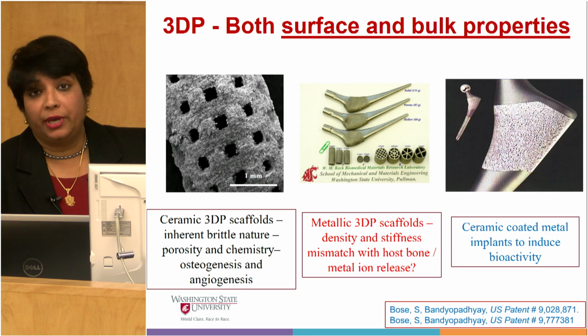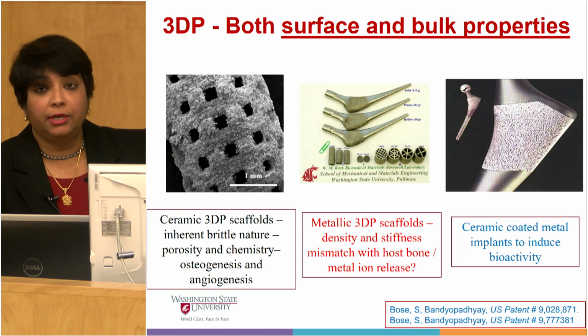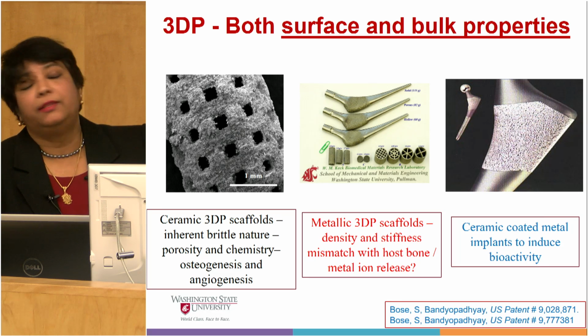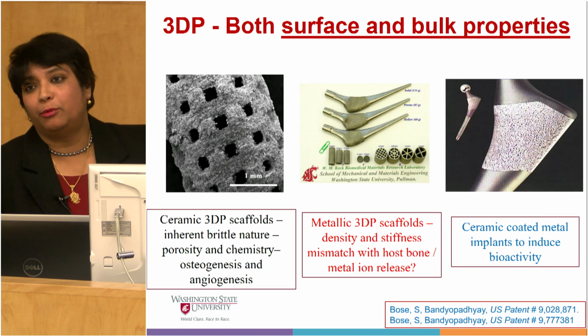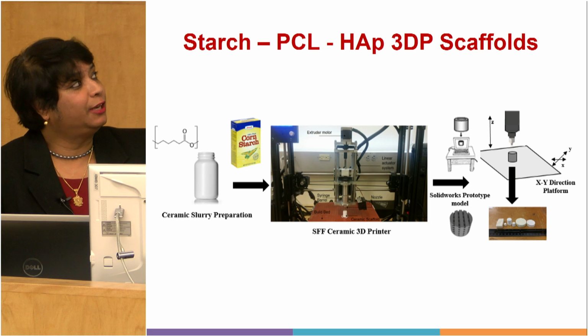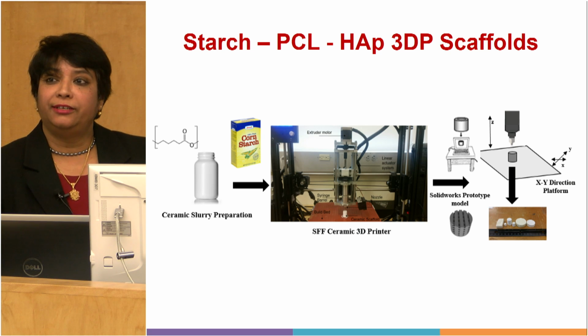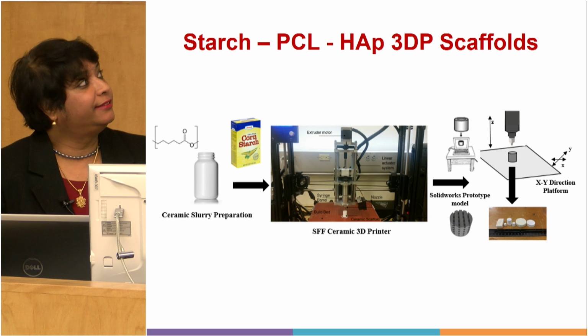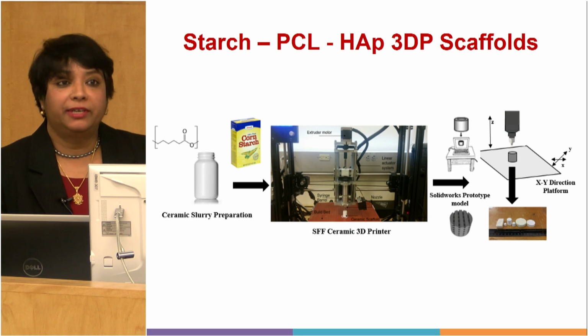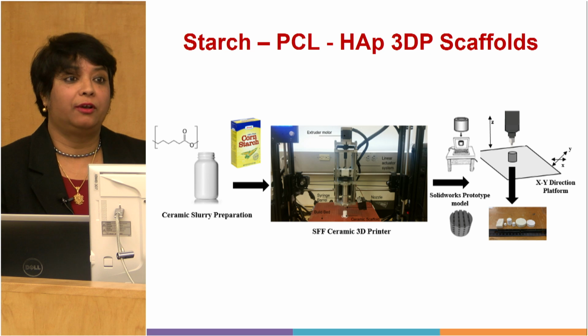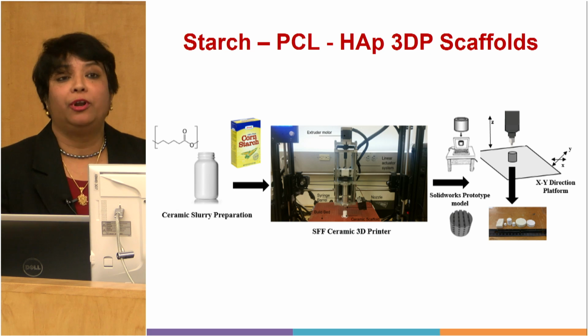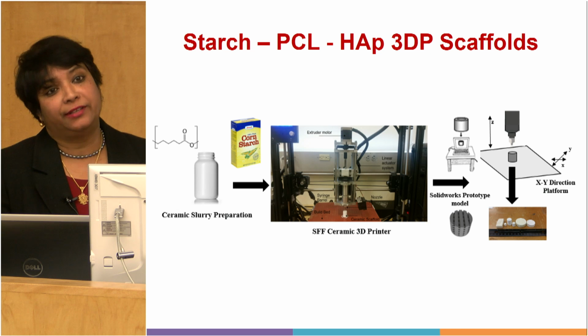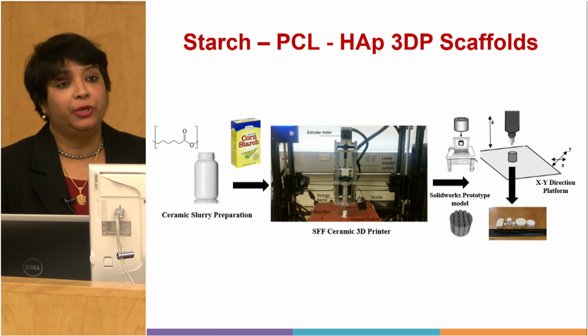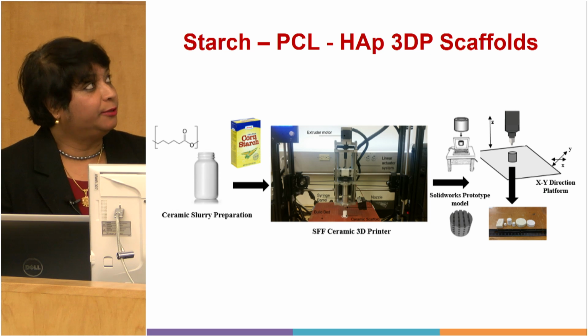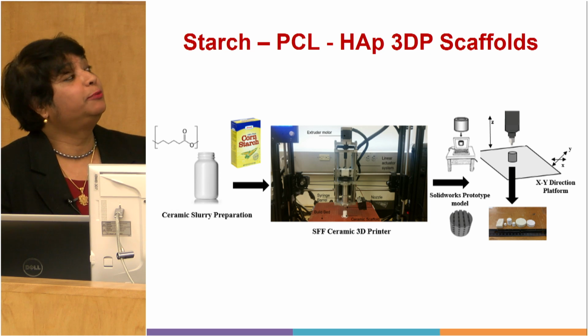So to address the brittle nature of ceramic scaffold, recently we have developed this double head printer in our lab. Bonnie and Caitlin are working in this area to make polymer ceramic composite to reduce the brittleness of ceramic, and we have already shown that we can get to cancellous bone without doing any post processing of these scaffolds directly from the printer. It is not published yet.